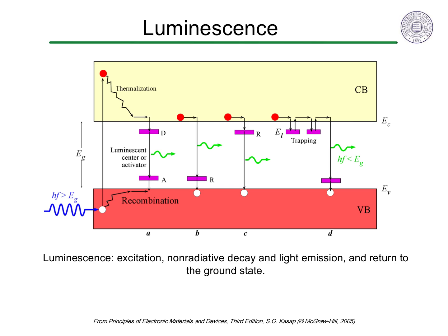Sometimes the defect states are called recombination sites because they facilitate the recombination of electrons and holes. Defect states can also act as trapping sites where the mobile electrons or holes from the bands can go but then become localized and no longer transport charge. After some time, the electrons or holes can be thermally excited back into the band and luminesce, extending the time of luminescence. Luminescence can also be initiated by other high-energy processes, such as bombardment with high-energy electrons, X-rays, or gamma rays.